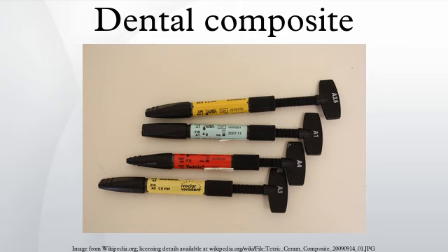The placement of composite requires meticulous attention to procedure or it may fail prematurely. The tooth must be kept perfectly dry during placement or the resin will likely fail to adhere to the tooth. Composites are placed while still in a soft, dough-like state, but when exposed to light of a certain blue wavelength, they polymerize and harden into the solid filling.